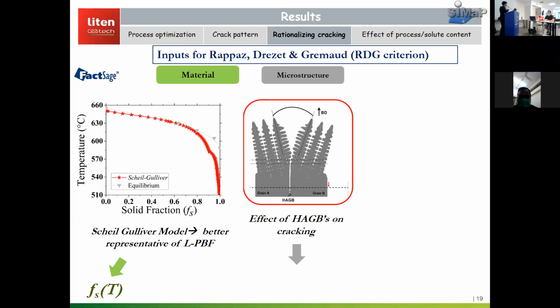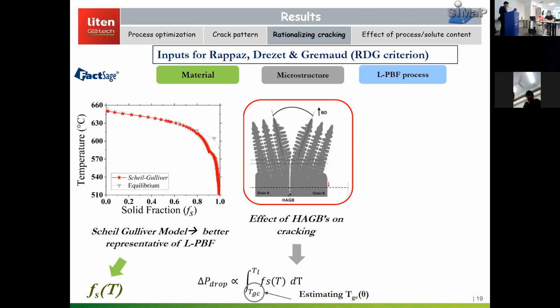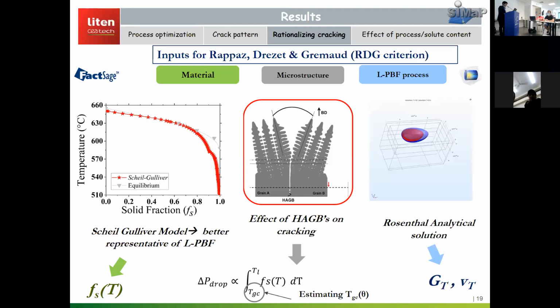The second input parameter is the microstructure aspect. We have seen in our experiments that high angle grain boundaries were cracking. So can we somehow include the misorientation aspect in the model? The way to do that is by modifying the lower bound, which is the coalescence temperature. And if we are able to identify this temperature as a function of misorientation, we can take that into account. The last aspect is the L-PBF process parameters. For this, we relied on simple Rosenthal analytical solutions to get a notion of thermal gradients and solidification velocities.